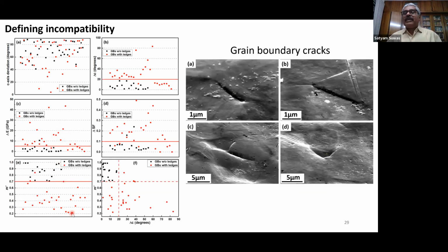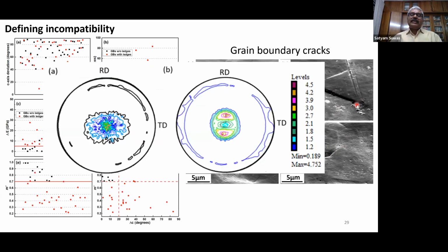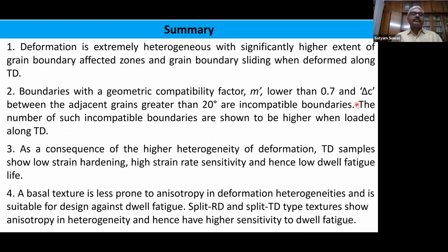And then we thoroughly examined the samples more carefully, and this time we saw the cracks, and it was like catching a fish in the sea. We saw that cracks are quite obvious, with a higher frequency of cracks in the case of the TD samples along the grain boundaries. Then of course the pole figures for the TD samples are just rotated by 90 degrees in this case. So the summary of this part of the investigation is that deformation is extremely heterogeneous, with a significantly higher extent of grain boundary affected zones and grain boundary sliding when deformed along TD as compared to RD.